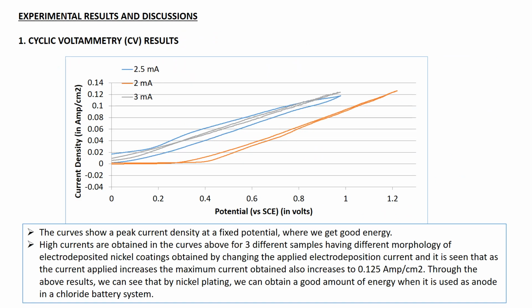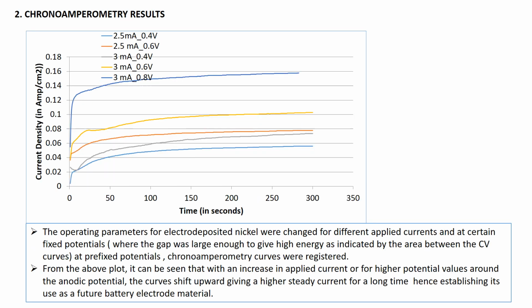Coming to the results for cyclic voltammetry, we see that the curves show a peak current density at a fixed potential where we get a good amount of energy, and high currents are obtained in the curves having different morphology of nickel coatings obtained by changing the electrodeposition current. We can see that as the current applied increases, the maximum current obtained also increases to around 0.125 amperes per centimeter square. So we can say that we can obtain a good amount of energy when it is used as anode in a battery system.